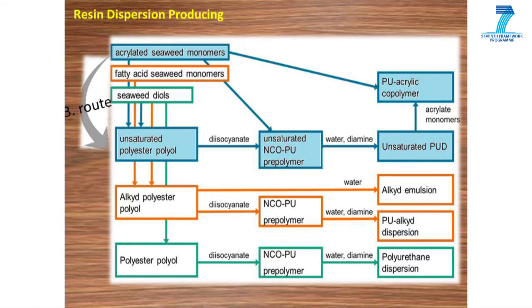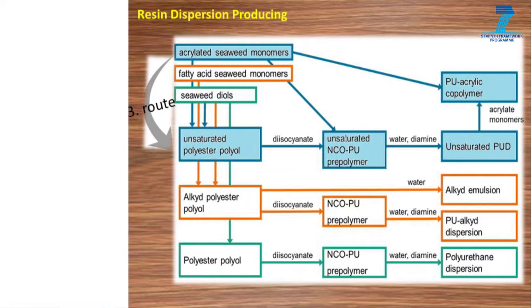The third route is about another hybrid system of polyurethane and polyacrylics. In contrast to route number 1, we use some unsaturated monomers in the polyester backbone or alternatively in the polyurethane backbone. Afterwards, acrylate monomers will be polymerized in the presence of the unsaturated polyurethane dispersion by emulsion polymerization technique. Seaweed monomers can be used as before in the polyester part or after functionalization as acrylated monomers.